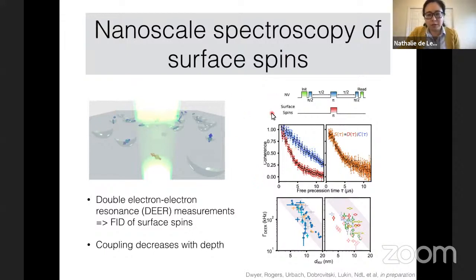So this is a second story about trying to do nanoscale spectroscopy of spins that reside at the surface of diamond. Our main tool here is double electron-electron resonance measurements, where you do a Hahn echo on your NV center, and then you apply a selective pi pulse to another bath of dark spins that you can't address optically. If you just apply this Hahn echo, you get this decay. But if you put in this pi pulse that selectively addresses this other bath, you get this decay. Now if I divide out these two curves, I get basically the free induction decay of these surface spins.